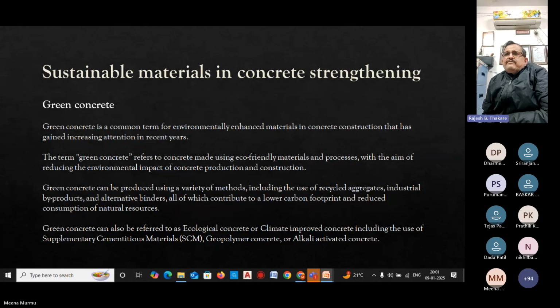It also improves the workability, strength, and durability. Also reduces the heat of hydration, making it suitable for mass concrete applications. As I informed, rice husk ash is a byproduct of rice milling, which is rich in silica and can also be used as an SCM in concrete.